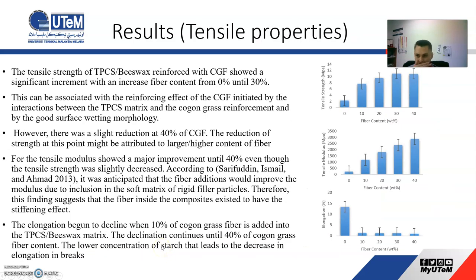Okay, in terms of the mechanical properties, as you can see in the figure here, the strength was increasing. It's significantly increased, from 0% here until 30%. So it's 5 times of improvement in terms of the tensile strength when we employ the cogon grass fiber. So this can be associated with the reinforcing effect of CGF, initiated by the interaction between the TPCS matrix and the cogon grass reinforcement, and by the good surface wetting morphology. However, there was a slight reduction at 40% of CGF here. This can be attributed to the higher content of the fiber. For the tensile modulus, it's a very good improvement. The material becomes more stiff, more stable.